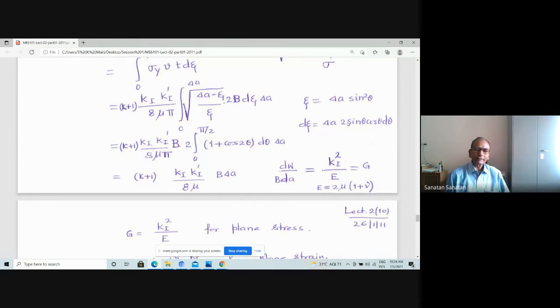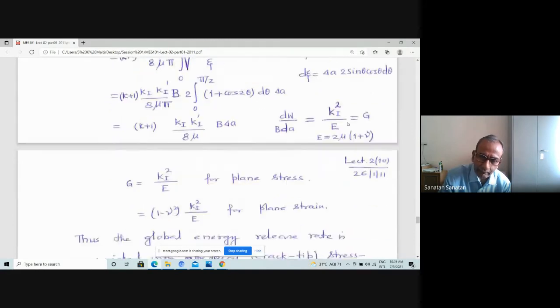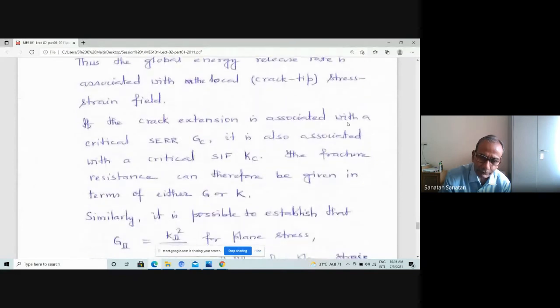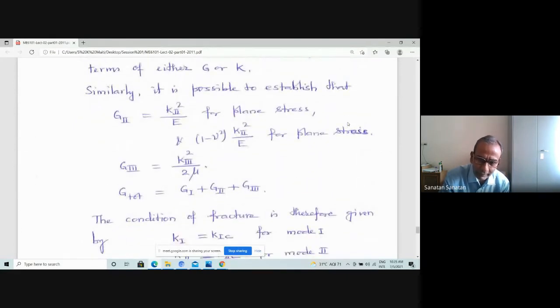See, that concept of single-person dominance is now nullified. It is what you call a democratic view. It is not the stress at a point that is important in the case of failure of material. It is the distribution of stress and strain over a zone around the crack tip. So crack extension is associated with a critical stress strain field around the crack tip. So that democratic view of actual material failure is given by this theory. So that's how it became a new way of understanding material failure, and it also overcomes the question of giving importance to stress at a point. It is stress around a zone, and that's what it is.